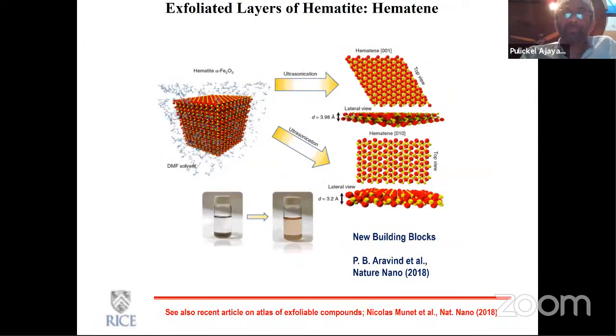Even if you don't have layered materials per se, there could also be approaches that allow you to break down or cleave along certain crystallographic planes and create extremely thin layers, which could be very similar to the layered system that we're talking about. Again, this is just an example to show one of the typical procedures we use to create these two-dimensional materials. That is essentially chemical exfoliation.